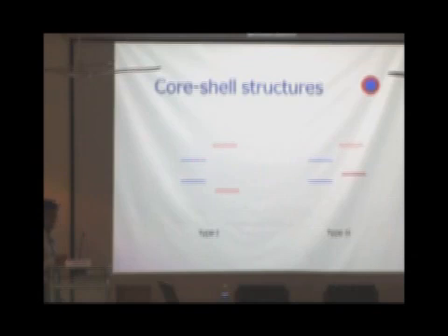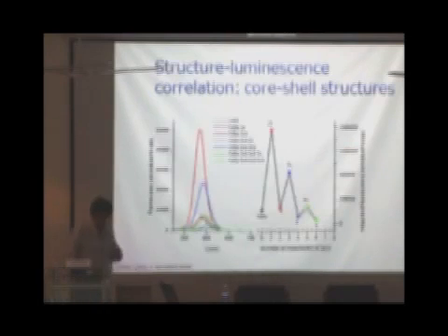So that means they have a greater chance of recombination. So you'll get much better luminescence efficiency. So these type 1 structures are much better for use in light emitting devices. Whereas in type 2 structures, where you have such band offsets, the hole would like to float to the top over here, and the electron would stay over there. So you have separated the charges, and those structures are more feasible for photovoltaic applications. So here I'm going to discuss light emitting materials.